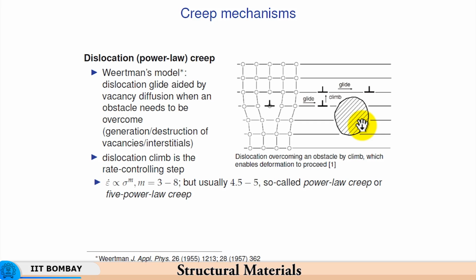So, avoidance of the obstacle is facilitated by dislocation creep, where dislocation movement is the one that governs the strain rate. The faster the dislocation movement, the faster is the strain rate, and the strain rate reduction due to the dislocation getting held up at an obstacle is prevented, or one can circumvent this obstacle by dislocation climb. Many times what happens is the interface between the obstacle and the matrix comes under heavy strain as the dislocations get piled up at that interface, and finally that interface itself gets damaged, and then the dislocation can circumvent the obstacle and finally move forward.